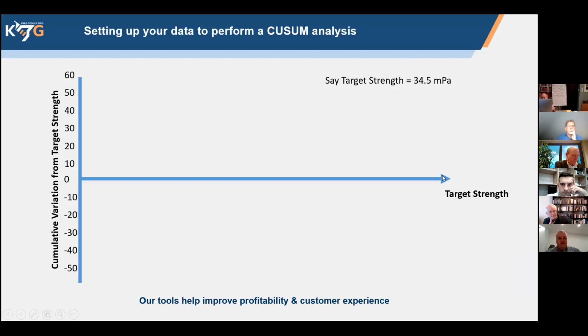Then the target strength is along the x-axis here, and the CUSUM remains 0. So if all your results came to exactly the right target strength, in this case 34.5 megapascals, the trend line would stay flat at 0. Of course, we know that you very seldom get 2 test results in a row that give you the same result, let alone the same test result within a batch of cylinders or cubes.